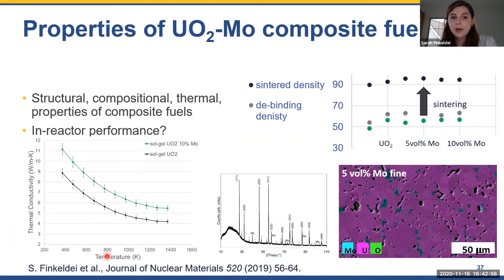And if you look at the thermal conductivity dependent on the temperature, we observed a huge bump in the thermal conductivity for molybdenum-doped uranium dioxide, a potential fuel candidate. And in fact, we also observed already a bump in the thermal conductivity just for a purely uranium dioxide specimen that is fabricated from a sol gel precursor. And we are currently trying to understand where this bump in thermal conductivity comes from.